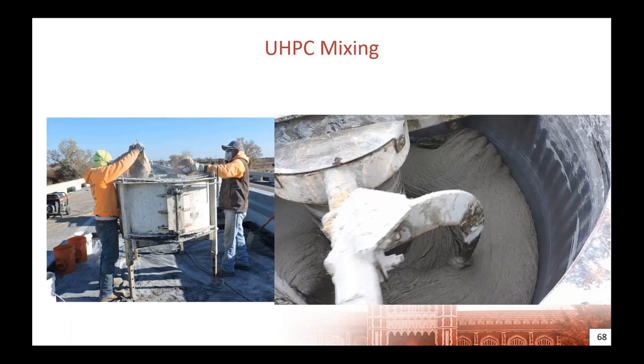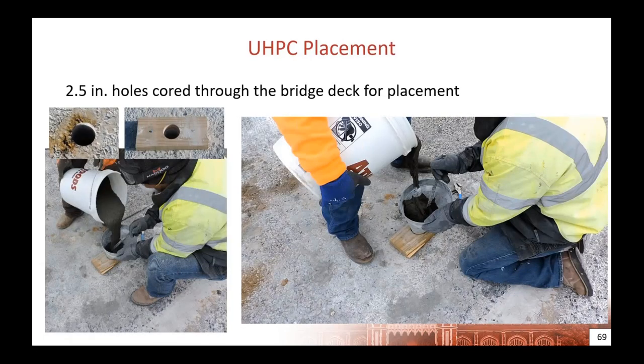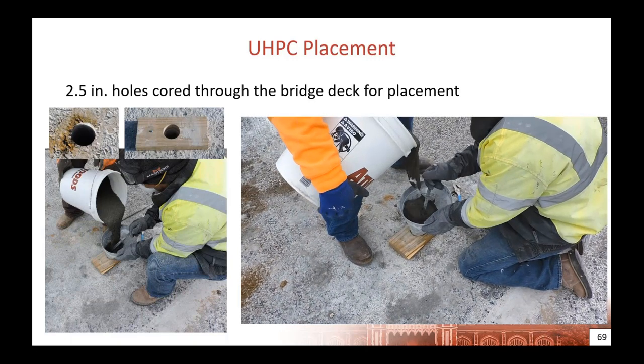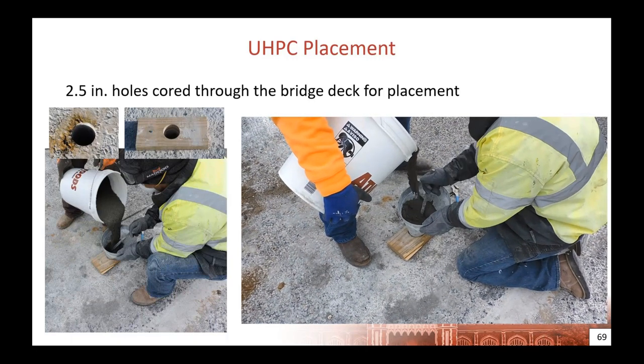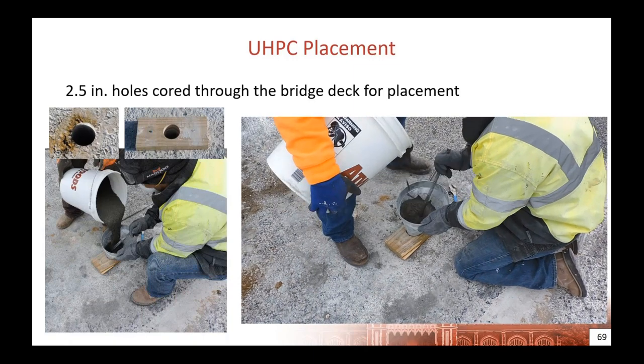But because of that fluidity, we were allowed to use a unique placement method. This material was placed through 2.5 inch diameter holes cored through the bridge deck that was centered over each of the continuity joints. And this particular material was required to pour above the top of the finished road. So the 2x4s were placed so we could increase the height.